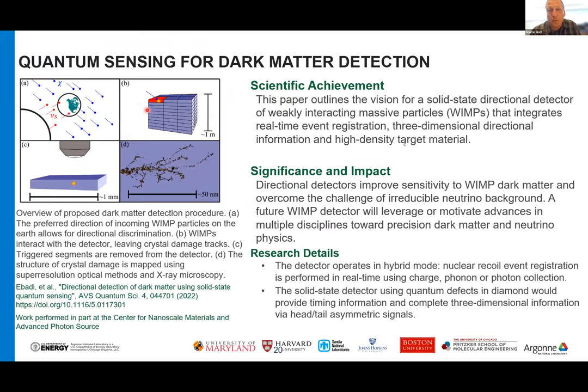They're also going to be using this for dark matter detection. I was pretty excited about this because this is the first time I can put light years and nanometers on the same view graph, of course. The idea with these weakly interacting massive particles is there's a lot of undesirable background coming from the sun in terms of neutrinos, but that's all at a fixed planar intersection to a detector, depending on the Earth's rotation. And most of the dark matter is actually coming out of plane. And so if you can recognize and find the aspect ratio of these defect tracks that are embedded in the diamond, you can eliminate most sources of noise in the detection of dark matter. So they're planning to use X-ray microscopy for that with 1 meter cubed of diamond because their funding is larger than my funding, of course.